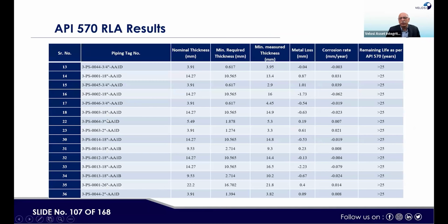So here the results are shown, not all calculations are shown. For most of the piping system, we list nominal thickness, minimum required thickness, minimum measured thickness, metal loss, corrosion rate, and then accordingly remnant life. The remnant life for all the piping system was greater than 25 on the linear rate basis. Here we are not talking about cyclic service, but about metal loss related remnant life, not thermal cyclic related remnant life. It was found within acceptable range, because wherever defects were, those pipes were already replaced or repaired by the client.